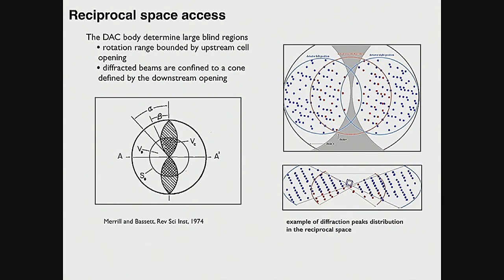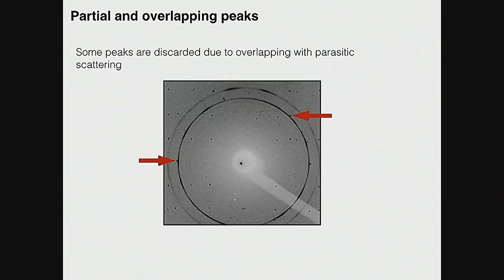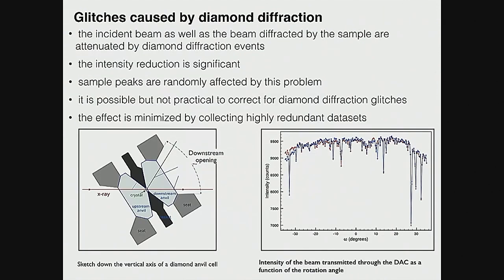So what can you do about it? Well, one solution can be to have different crystal orientations in the same dataset or in different experiments, and then you have to scale and merge your data. You have this parasitic scattering, the Bragg rings from the metal that creates the sample chamber. So your peaks are overlapping and you lose them, so you're losing information once again. You have glitches here too.